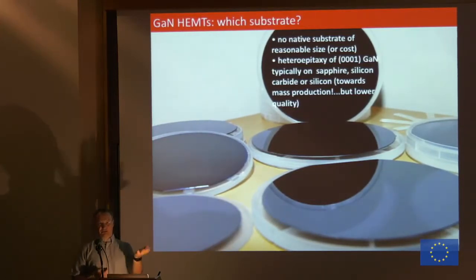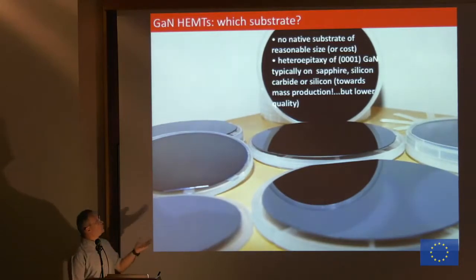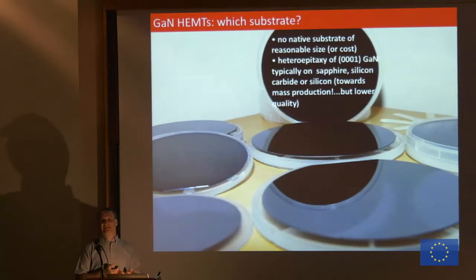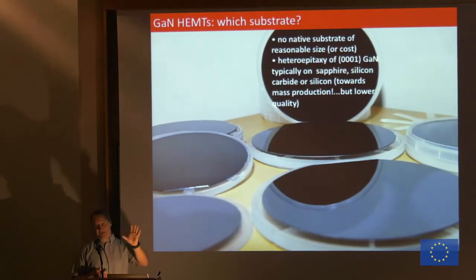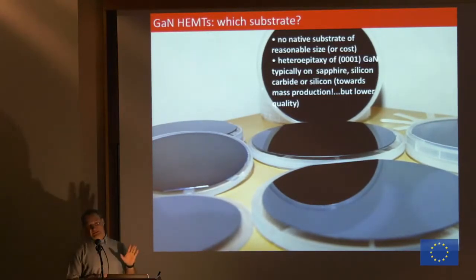So then we need a substrate. At the beginning it was sapphire, but sapphire is a non-conductive substrate, and specifically for thermal it is very bad. So the best compromise was silicon carbide. So the first devices that were processed in the past were gallium nitride over silicon carbide. Because the material is pretty similar, the lattice mismatch is small, we have a lot of advantages, and very good thermal dissipation. So that was perfect.